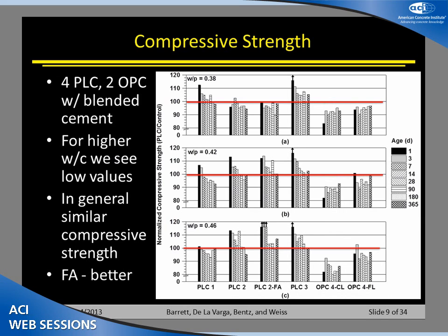And what these plots are is a plot of the properties of the Portland limestone cement divided by the same cement made with a conventional clinker. So if you get a value of 100%, that means that the Portland limestone cement is completely interchangeable with what you've seen with the ordinary Portland cement. To make that a little bit more clear, I've drawn through on a red line the 100% value, and as we go down this particular series of symbols, we go from age of 1 day up to 1 year properties.